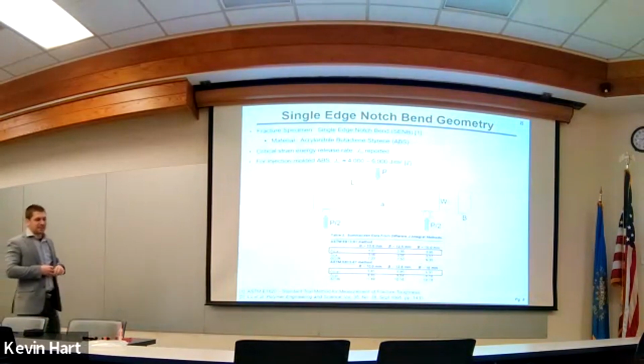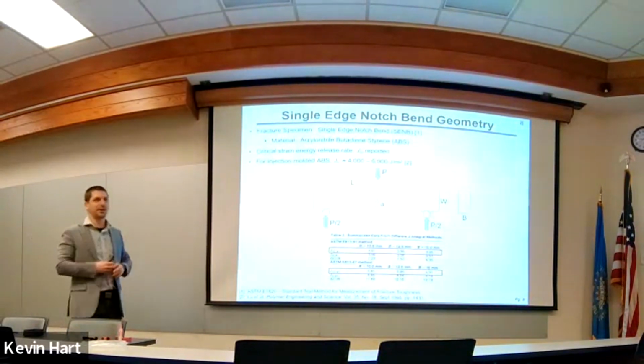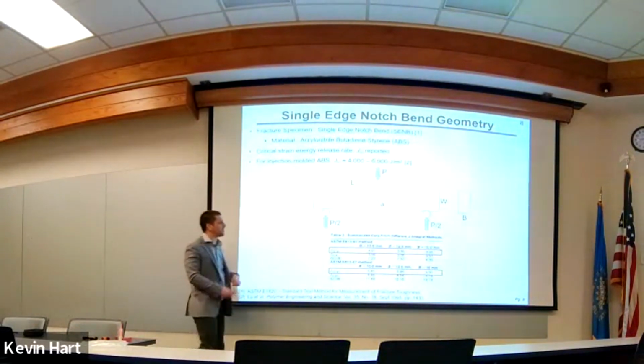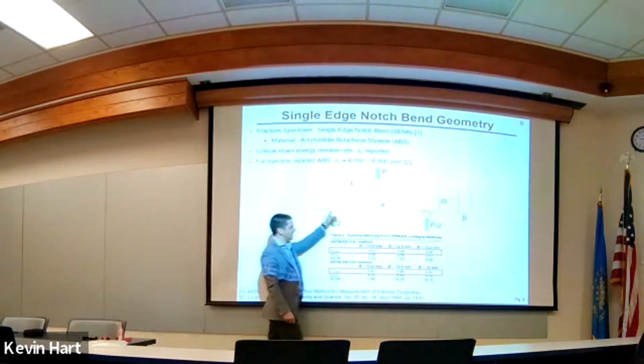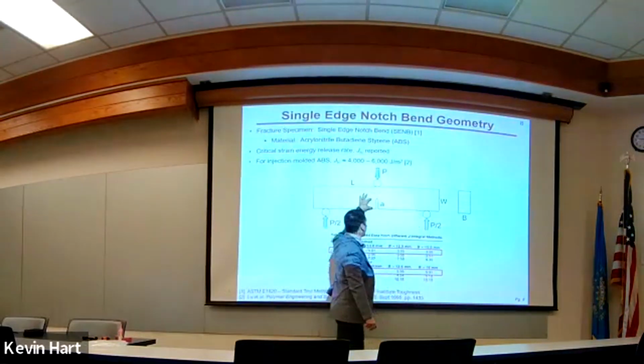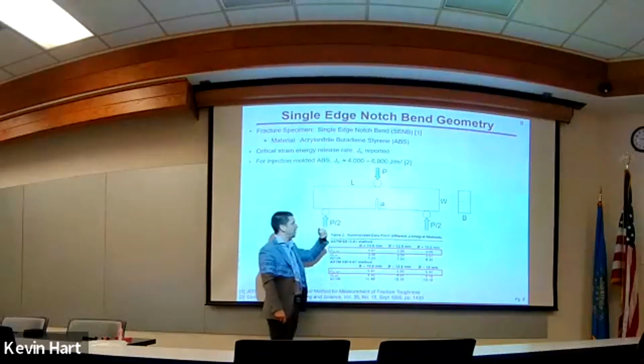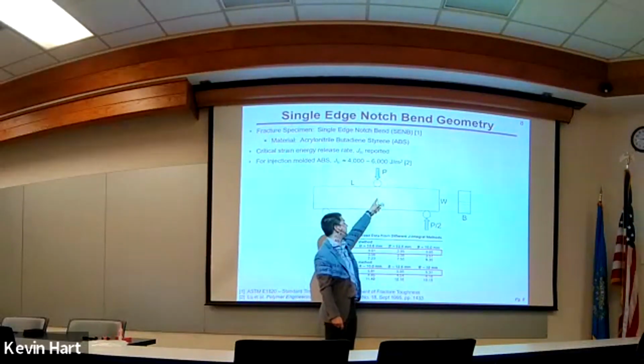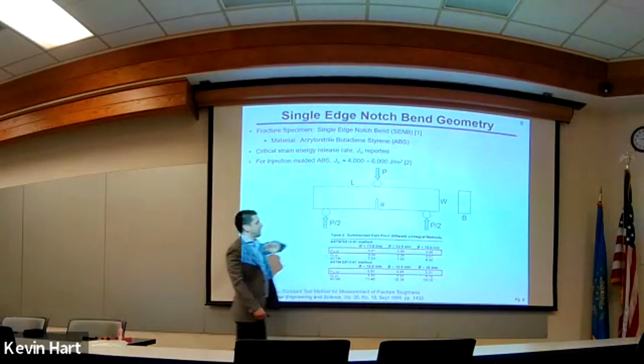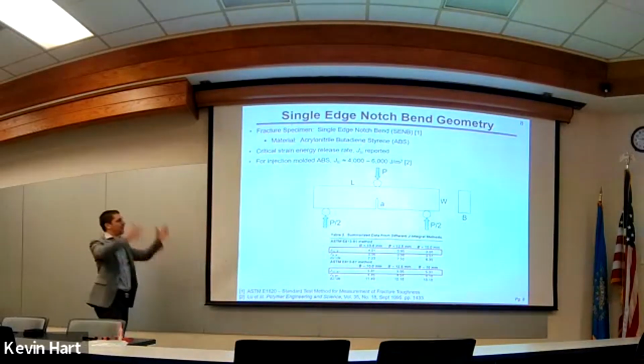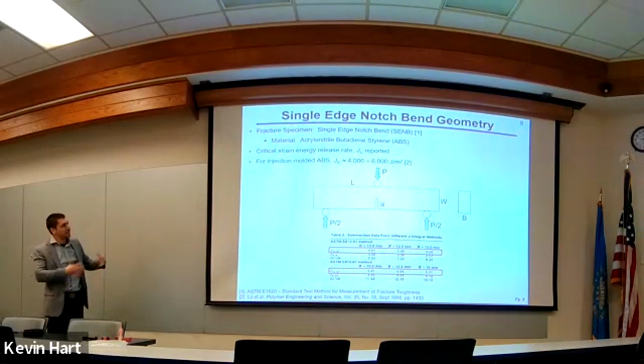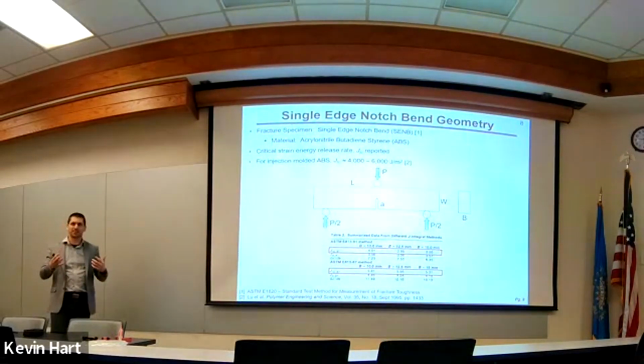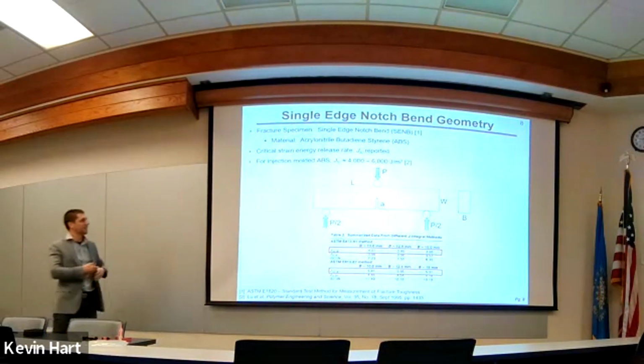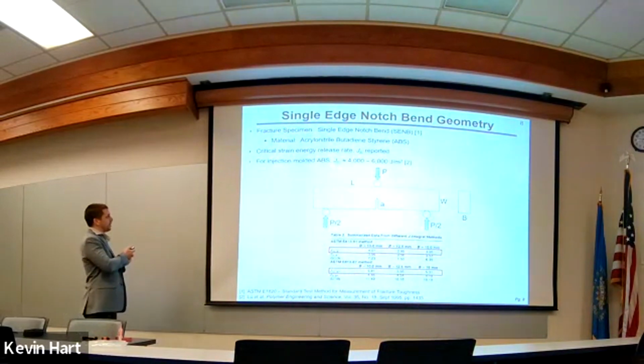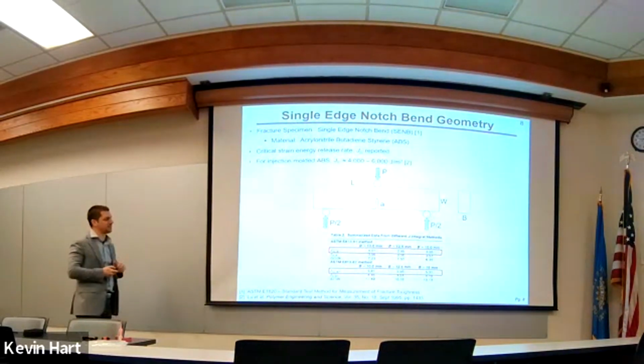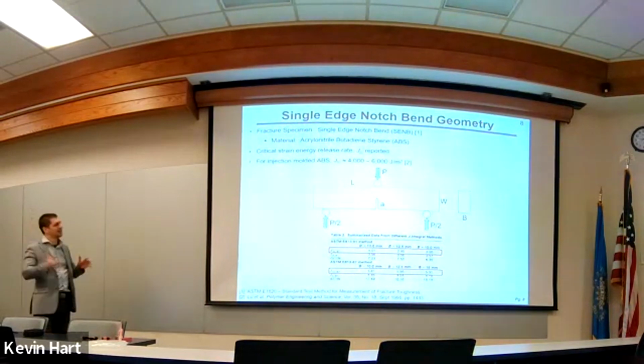So one of the first things I did is I manufactured a fracture specimen. This is called the single edge notch bend specimen, SENB. It's just this rectangular prism that looks like this, and it has a small notch on the underside. You put this thing into 3-point bend, and there's going to be a crack that propagates from this notch tip forward. You can use cameras to look at how far the crack is going, and you can get a metric associated with how much energy it takes to propagate a crack a certain amount, okay? That metric that you might be interested in is called the critical strain energy release rate. It typically has a variable J1C or G1C.